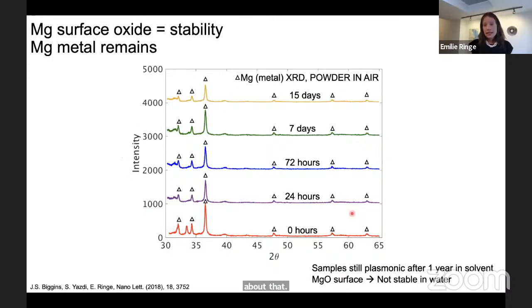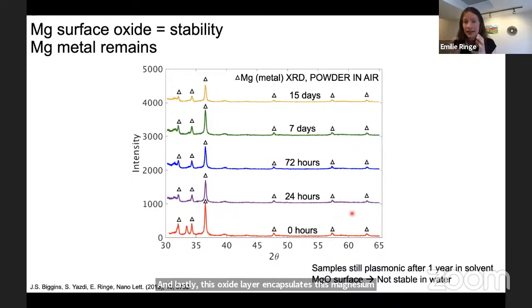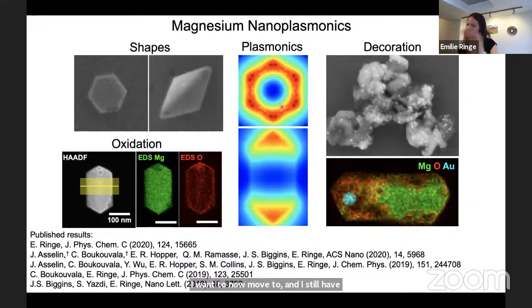Lastly, this oxide layer encapsulates the magnesium metal layer, and it stays like that. We can dry these particles in air, leave them on the bench for a while, do powder XRD, and still see the signature of magnesium metal in these structures. They're stable in organic solvent. The only thing they're really not stable in is water, because the magnesium forms a water-soluble magnesium hydroxide and dissolves, which is not a bad thing for biomedical applications, for instance.